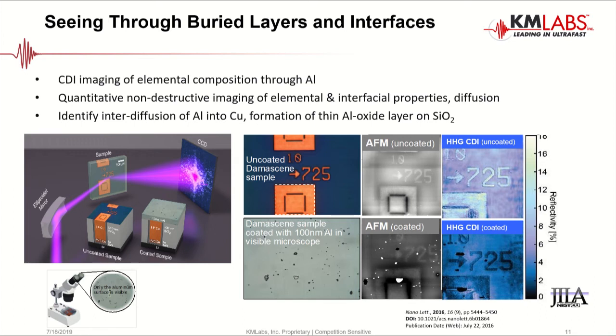The power of CDI is that, depending on the elemental composition of that coating layer, we'll be able to see typically tens of nanometers, or in some cases a few hundred nanometers, down beneath the surface, and see really clearly the types of effects that are happening there. And so what we can see here is this 725 pattern quite clearly in both the uncoated and coated case. We actually note there's a contrast inversion here of those numbers relative to the substrate behind them. This is indicative of some sort of interdiffusion or interlayer formation, where we're probably getting some reaction products forming at the interface of the different chemical layers here. Coupling this with some modeling of the reflection process, we can maybe even tease out what kinds of chemical compounds or interfaces we're starting to form.